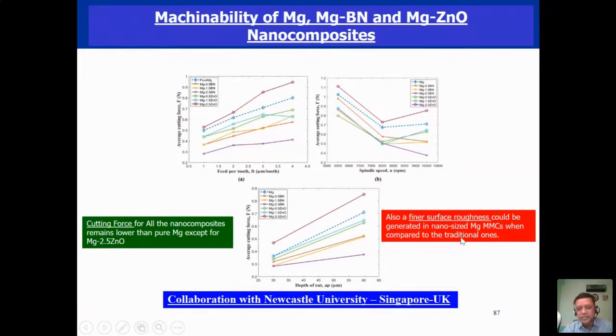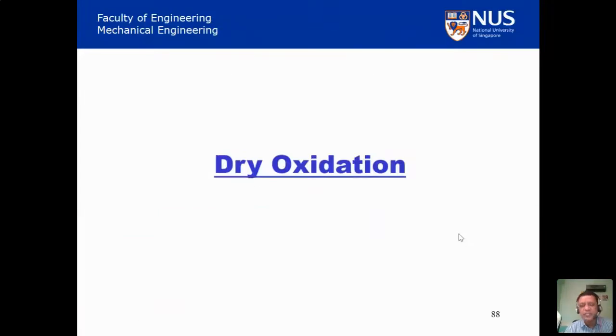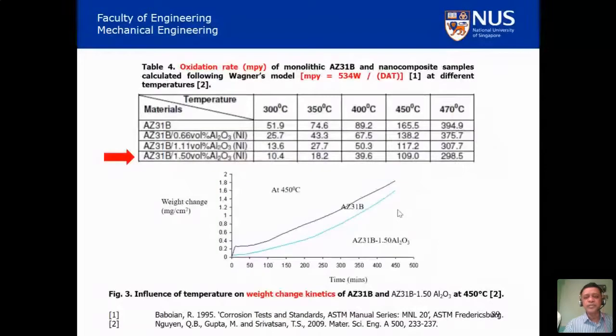And they also get the fine surface roughness. So that means you can machine these materials at the same or better speed than the conventional material. Corrosion is another issue. When you expose your materials to the dry condition, it is called oxidation. And if you look at this graph, the blue graph here is the one which corresponds to the composite material, which shows that the oxidation resistance of composite is better.